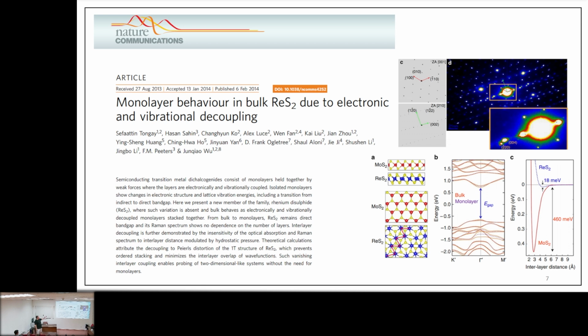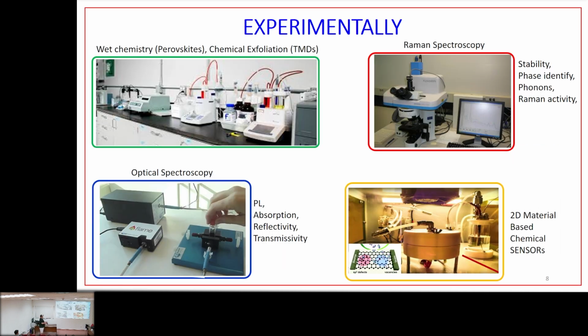So here they were happy in the end because everything was clear. And then I suggested formation of this dimerization. Then after some high resolution TEMs, they got this. They confirmed this dimerization. Then the scenario was complete. So you can use DFT in different fields.